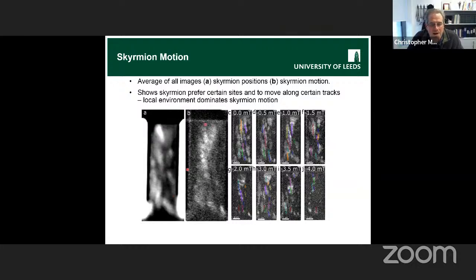This image here is if we take sort of differences and add them all together. So here the bright regions are where you're likely to find Skyrmion motion if you push them. And again, you can kind of see these tracks. So there's a sort of material science thing to work on here, which is, if you can get a very beautiful material that's very flat, then the Skyrmions can move around more easily. And in fact, this sort of diffusion in these flat landscapes has been seen in simulations.